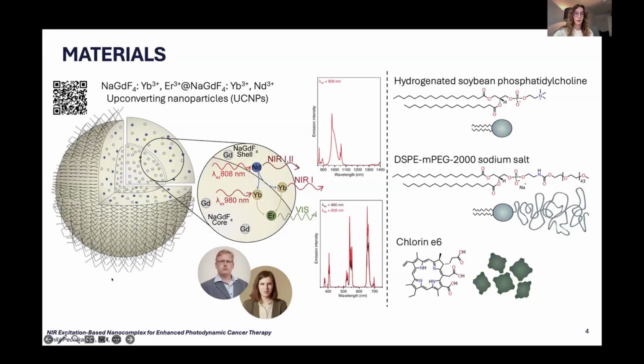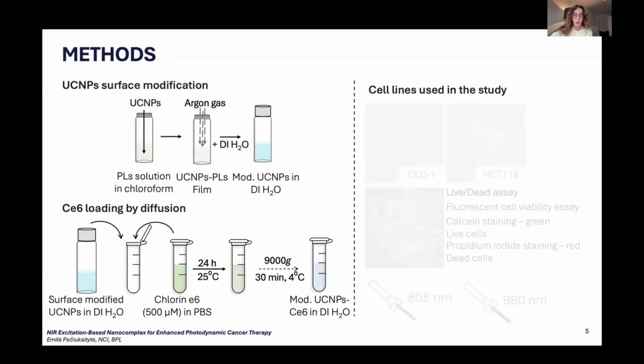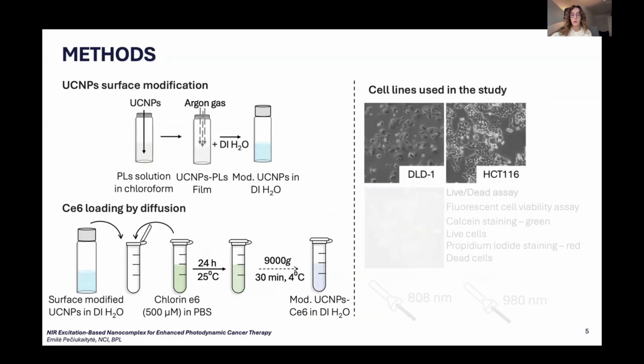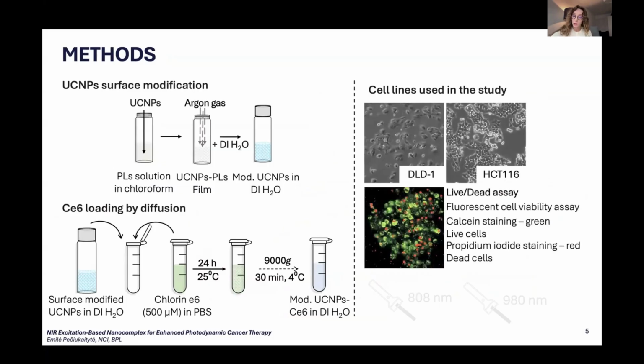More about the nanoparticle synthesis you can find if you scan the QR code. Upconverting nanoparticles were first coated with phospholipids through film formation, and chlorin e6 was then loaded into the coating via passive diffusion. We used 2 human colon cancer cell lines for biological evaluation. To assess therapeutic response, a live/dead staining assay was performed. During the whole study, we used 2 different sources of light: 808 and 980 nanometer laser light.